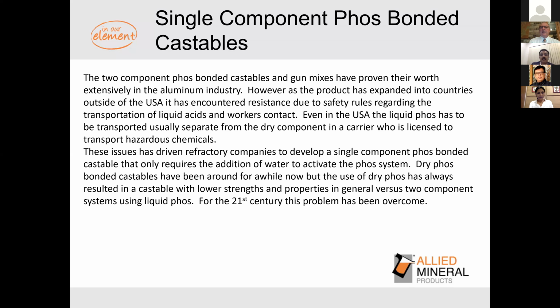So the contractors that put this material in have asked, can we make this type of product, but use water to make it into a concrete type consistency, something that you can pour or spray, but it's activated with water as opposed to phosphoric acid. It was not an easy challenge, but I'm happy to report that in the 21st century here, we have answered that challenge and have developed a single component water activated Phos bonded castable and gun mix.